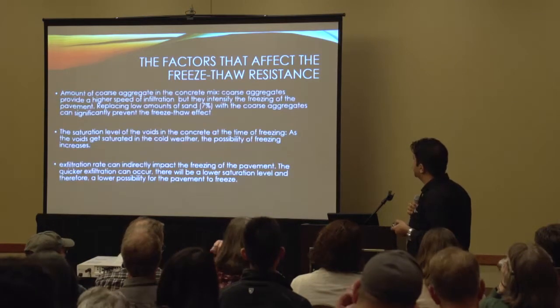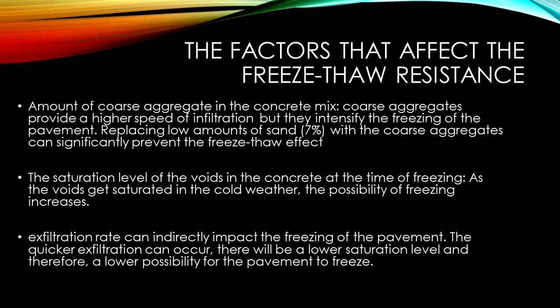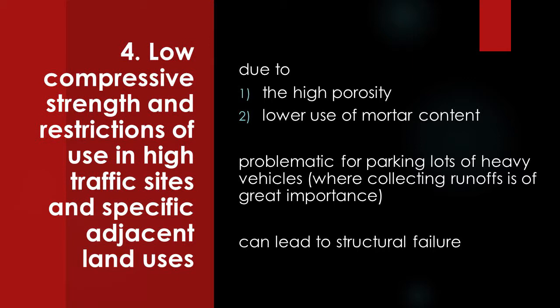The factor that affects freeze-thaw is the amount of coarse aggregates. Studies show that although coarse aggregates are better to increase the permeability, using low amounts of fine aggregates could have a positive impact on increasing the resistance against freeze-thaw. The percentage given is 7% of fine aggregates. The low compressive strength is a result of high porosity of these pavements and lower use of mortar content. So it can lead to structural failure, and we need further research to improve the compressive strengths of these pavements.